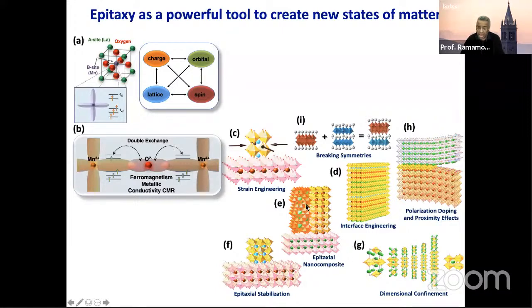I can create vertical nanocomposites, looks very much like a cigarette box, with epitaxy as a driving force. I can stabilize metastable phases using epitaxy. Or I can do doping at very, very small scales by proximity effects. You know, I can have a semiconductor in contact with the ferroelectric, or I can confine things to very, very small dimensions. So the power of epitaxy in creating model systems has been a dramatic boon for all of us materials physicists. So this is what we did.